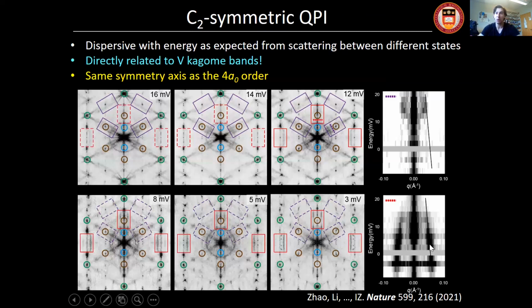So you can see there's a lot of information there, but no matter how you look at this, the first thing that you notice is this kind of C2 symmetric QPI. These are twofold symmetrized Fourier transforms, but I can assure you that somewhere in my hidden slides I have non-twofold symmetrized, and they look virtually the same. So there is this kind of primary axis along which the scattering is enhanced. I want to note it's the same symmetry as the 4a0 order. Okay, so it's in the same direction. This reflection plane, or the reflection line, is in the same direction. And based on the theory, we know it's directly related to the Kagome bands.